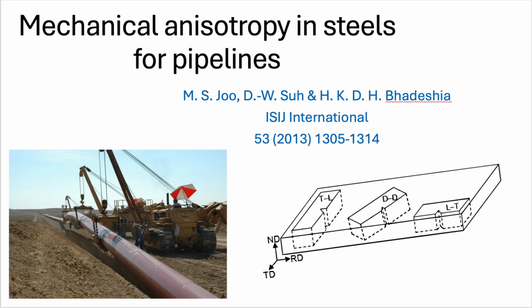Right, it's complex. Usually at higher temperatures up on the Charpy upper shelf where you want ductile behavior, splitting is bad news. It acts like a premature brittle failure. It lowers the absorbed energy. Okay, that makes sense. Lower toughness. Bad. But if the splitting happens at low temperatures, down in the brittle transition range, sometimes it can actually help.